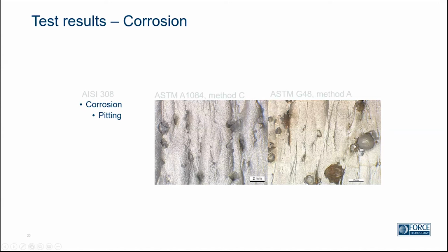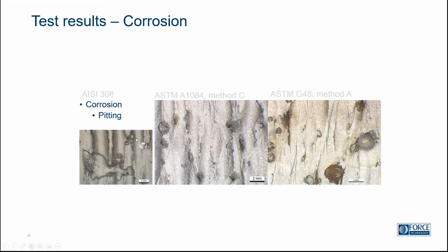And then to the question whether it's necessary or not, here we conducted some immersion tests, where we can see that in some of the areas where before we saw copper deposition near these little droplets, corrosion has initiated here. That is also because these tests will naturally initiate at sites where you have a crevice or a small pit, and you will see exactly the same thing if you have a small pore in a weld when testing that. Testing welds with G48 is extremely common, and in a lot of ways you can say this is similar to a weld.